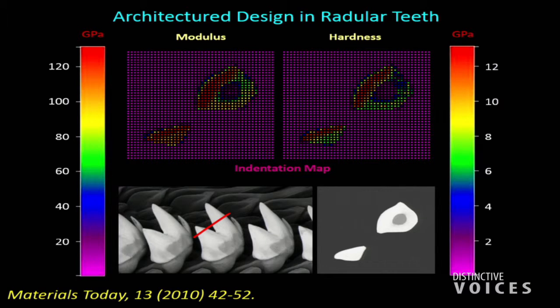But if you look at the tooth, the leading edge of the tooth actually has quite a high hardness. And the trailing edge of the tooth is softer. We think that design is there for a self-sharpening reason, so that as it's rasping, the leading edge is going to stay intact, but the trailing edge will slowly wear away. So it actually is always sharpening.